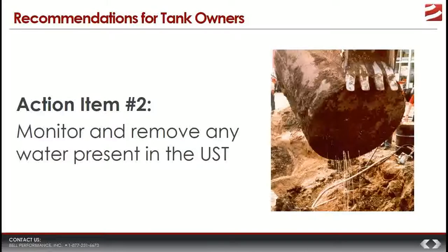But when you start getting above that, the general rule of thumb that groups like the Steel Tank Institute say is that if you get an inch of water in your tank, you're at the point where you've got to get that out. If you let it go even longer and you get 2 inches of water, you need to shut that tank down. Don't let anybody get fuel out of that. Get that water out. So those are just some reference depths to give you some context here.